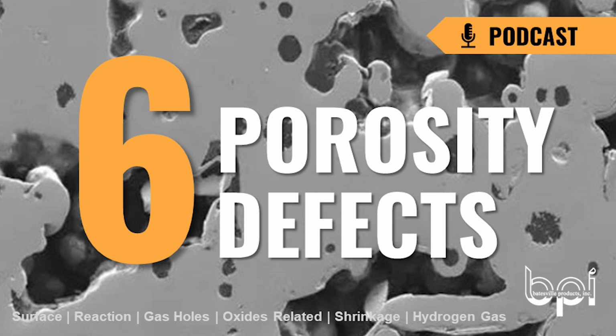Brad, what are we talking about here when we're talking about surface porosity? Well, first of all, customers call almost all defects porosity. So what we're looking at here is some blisters on this slide where it's flaked away, dirt in the sand mold. Maybe Ernie can expand on that a little bit. Primarily it just lays on the surface in sand molds. It tends to be dirt if it's in the cope half of the mold, and then it tends to be a dross if it's in the drag half of the mold.